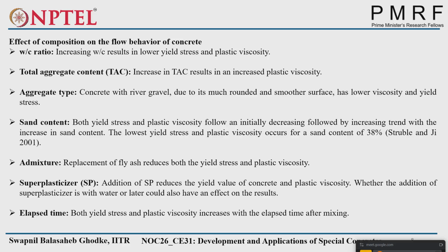Because of the hydration mechanism, as we saw, there is an irreversible part. Because of that, at each point, that is the 5 minute point, 10 minute point, 15 minute point, you will observe higher yield stress and higher plastic viscosity because of the increasing hydration mechanism. That is chemical bond improvement. Okay, that's why it is called time dependent yield stress.